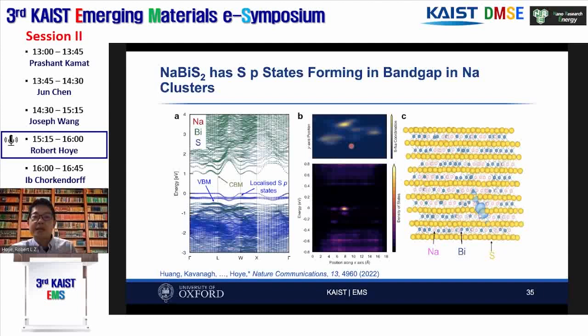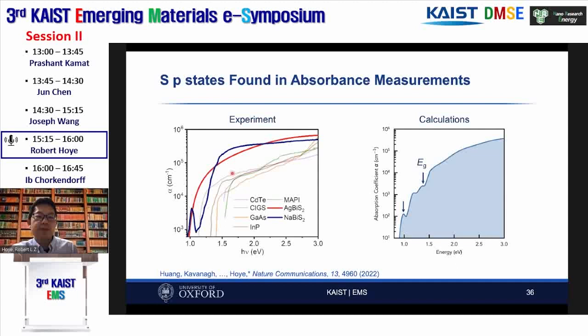We have a random distribution of sodium and bismuth. And so we have some situations where some sulfurs have a lot of sodiums coordinating around them. And when that happens, we have these p states forming within the bandgap, as you can see over here. And that is quite consequential. And we know this happens based on the optical absorption spectra.